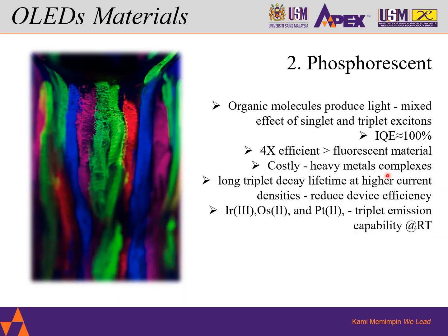The second one is phosphorescence. It produces light with a mixed effect of singlet and triplet excitons from the organic molecules, resulting in almost 100% IQE. It is 4 times more efficient than the previous material that I mentioned, which is fluorescent. However, it is very costly due to the use of heavy metal complexes. Some phosphorescent materials with long triplet decay lifetime at higher current densities may reduce the device efficiency. Ir, Os, and Pt are mainly used because of their capability of emission at room temperature. These are the heavy metals that we mentioned earlier.